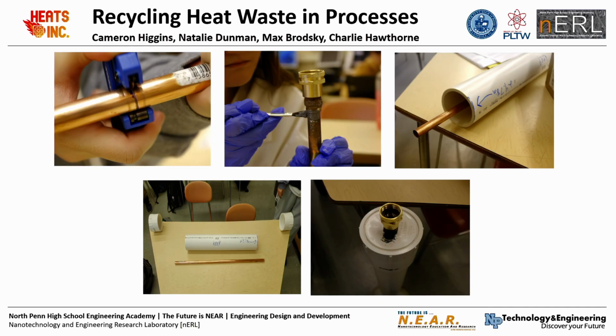To create a functional PCM battery, we used a shell and tube structure. To do this, we cut a copper pipe to fit onto a larger PVC pipe. Then we used PCM and poured and compressed it into the larger PVC pipe. The copper tube was sweated on both ends so that a hose could be attached to it, which you will see later on. To ensure that the PCM did not leak out, we sealed the tubes together using steel epoxy.